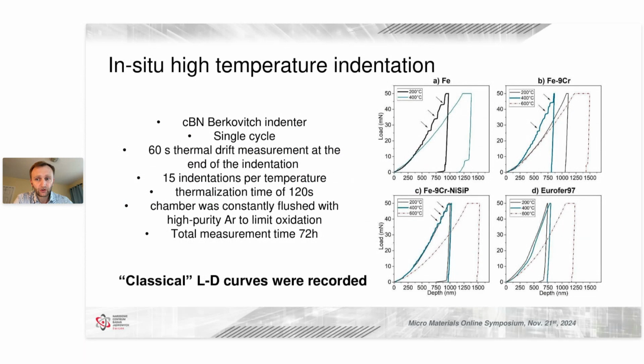As Nigel said, it is not necessarily easy to limit oxidation, as we could not record the signal for pure iron at 600 degrees, because at this temperature iron oxidizes very rapidly and very easily. When we analyzed the load displacement curves, we saw that there are certain bumps, or one may say steps, and these steps appear periodically, and we noticed that they appear only at a certain temperature per given material.